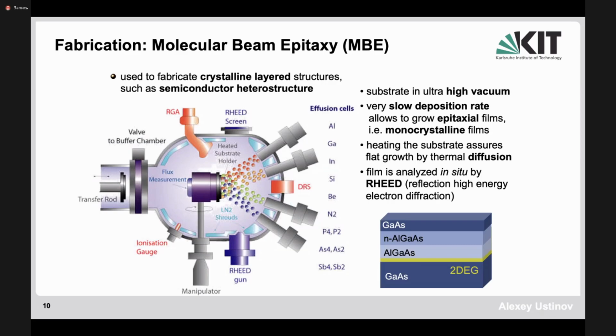And the technique to control that is the so-called reflection high energy electron diffraction, RHEED, which is basically controlling the order of the structure while it grows. So one can actually observe layer by layer growth of the structure and monitor this, and then guarantee the highest perfection of the growth during the process. This is really a very well established process, quite expensive, of course, but really established in the world. And in the semiconductor field, of course, there are always champion growers in different places where you could get the highest mobility